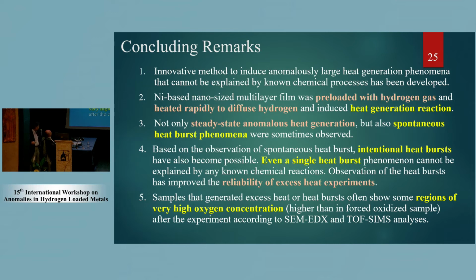Even a single heat burst phenomenon cannot be explained by any known chemical reactions. Observation of heat bursts has improved the reliability of excess heat experiments. Samples that generated excess heat or a heat burst often show some regions of very high oxygen concentration, higher than in the forced oxidized sample, after the experiment, according to the EDX and TOF-SIMS analysis.